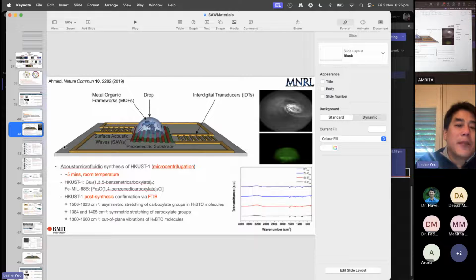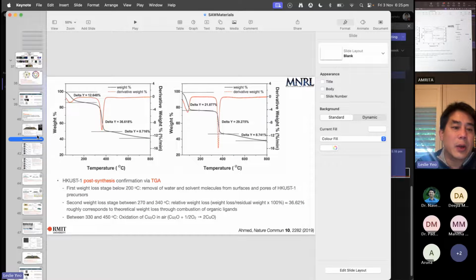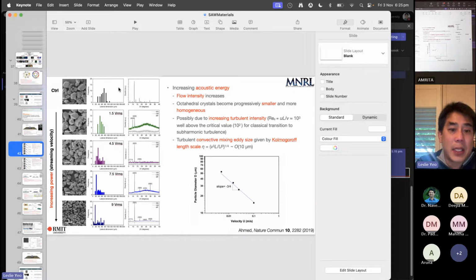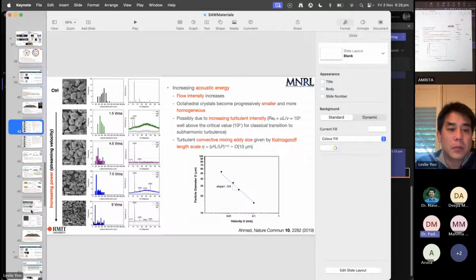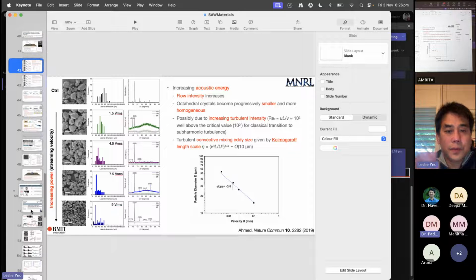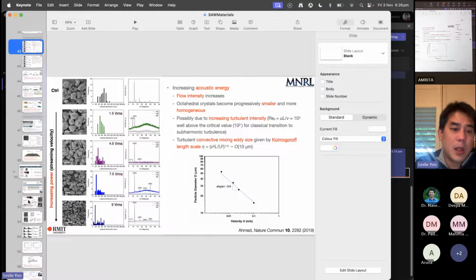Okay, let me answer the first question first. That's the easy part. With the HKUST, we did post-synthesis confirmation. We did FTIR, TGA and things like that, so we know it's HKUST. The powder XRD I actually showed you. It's HKUST, but a lot more oriented. The PXRD will be broad because it breaks up into nanoparticles, so line broadening will be there, that peak broadening. But if you take an FTIR, that confirms it will be fine. Yeah. Okay.